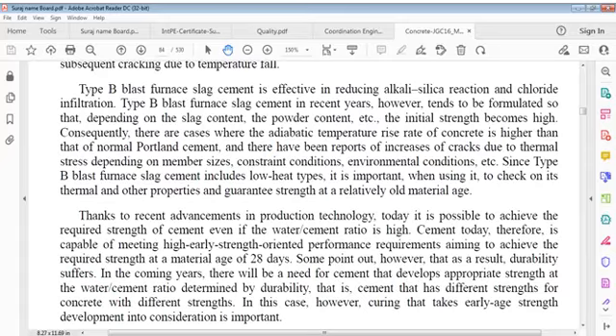Q is equal to K (1 minus e to power minus R(t minus t0)), where Q is adiabatic temperature rise at t degrees Celsius, K is maximum amount of adiabatic temperature rise in degrees Celsius, R is reaction factor in per hour, t is age in days, and t0 is starting time of hydration heat in number of days. That's only the formula.